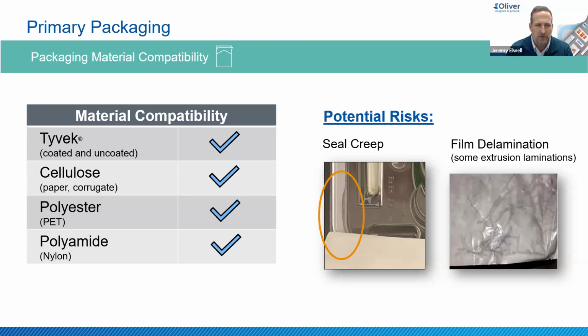And then when we look at risk with tray configurations, tray and lid, or pouch configurations, here's a couple we like to highlight. With any type of gas sterilization that uses vacuum, and chlorine dioxide does go at ambient, but also has some situations with vacuum, there is a risk of seal creep. And then also film delamination with some extrusion laminations, both of which we'll go into a little bit more detail in the next slide.